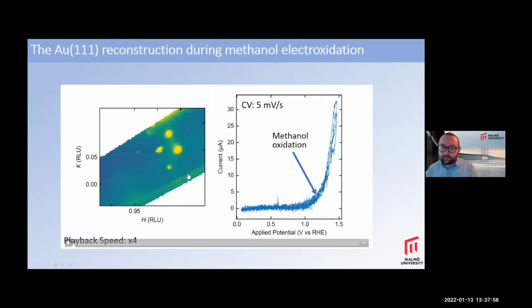And then we can look at this as we do a CV. I've sort of skipped a little bit ahead because not very much happens all the way up here. But this current is due to methanol oxidation, and you can see here you have the surface reconstruction rods, and then as we go into methanol oxidation, we can see that the reconstruction starts to lift, but it's still present quite far into